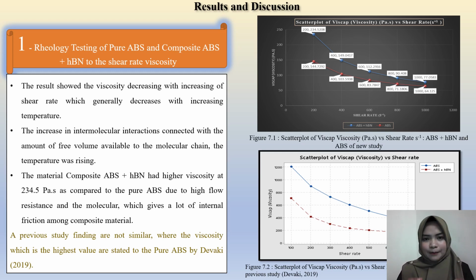The temperature was rising. The composite ABS HBN material had a high viscosity at 234.5 pascal seconds compared to the pure ABS, due to the high flow resistance and the molecular structure, which gives a lot of internal friction in the composite material. This result and a previous study's finding are not similar, where the higher viscosity value is stated for the pure ABS by Devaki 2019.